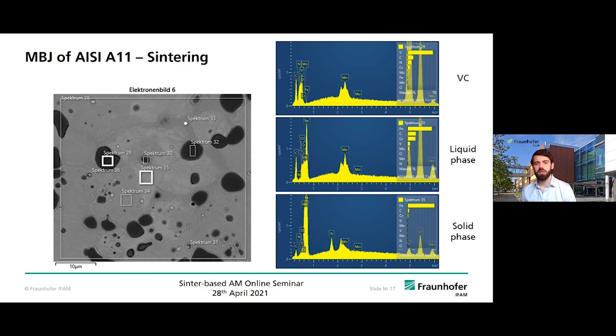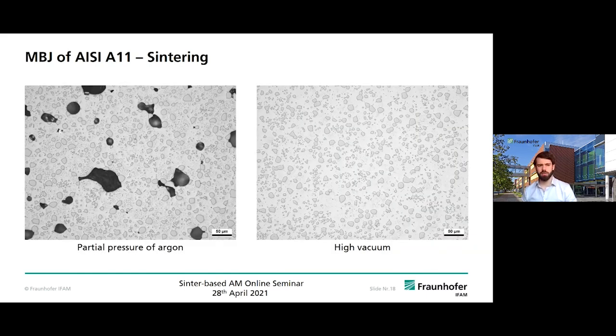Second, there was some liquid phase, and the liquid phase had a higher chromium, carbon, and vanadium content than the solid state. So we were not homogeneous when we sintered in the liquid phase and in nitrogen especially. So nitrogen was not the appropriate atmosphere for this material, and we switched over to sintering in partial pressure of argon. But as already mentioned, we got some closed porosity while still having some argon inside the green parts or brown parts. And further densification wasn't possible. So after the first trials, we switched to high vacuum, and we could reach full density, as you can say, with this material.